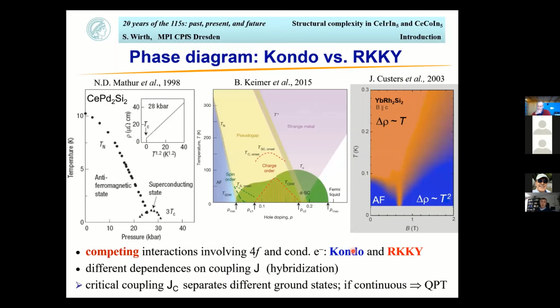Kondo would give you a non-magnetic ground state, RKKY would lead to a magnetic ground state. And since they have different dependencies on the coupling, you can actually play with them. And that's very nicely shown here in the phase diagram of CePd2Si2. I think also Piers already showed that.